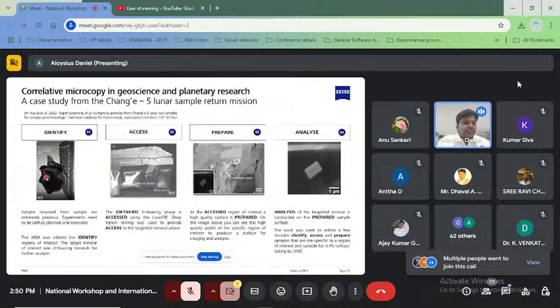During the screening process, their target was to identify the presence of zirconia. Wherever they were able to see a huge contrast difference, because the X-ray microscope always gives a contrast difference between high dense and low dense material, depending on the atomic number of every material present in the sample, they identified some bright regions where metal could be present. Once they identified those granules, they took them for laser followed by ion beam for exposing that region, and then that region was further subjected to chemical composition analysis, and they were able to identify that zirconia was present in the soil samples collected from the moon.